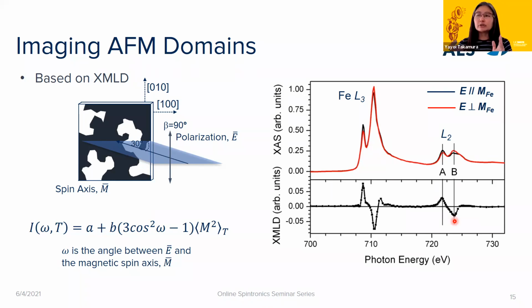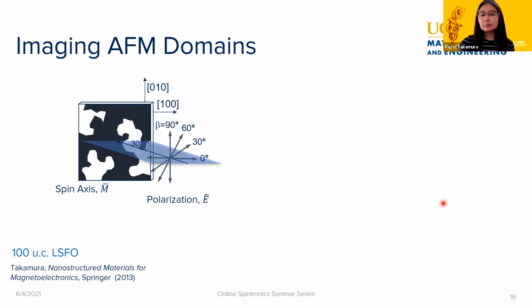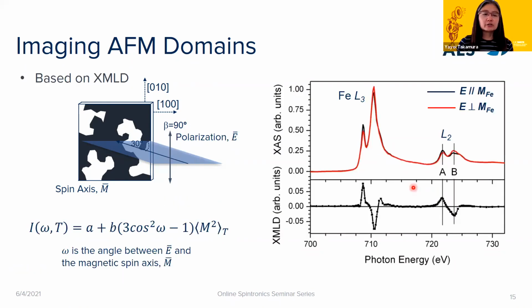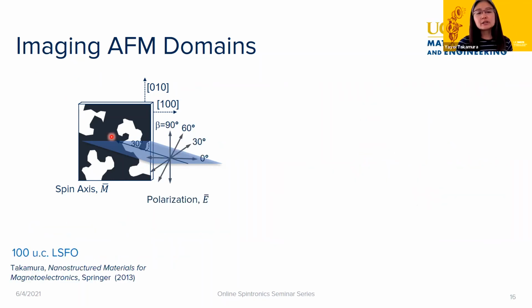And so then again, if we do this normalization, take the difference normalized to the sum, then we can get our dichroism picture. And so then what we'll get is that we can sort of map out locally what these antiferromagnetic domains look like. Okay, so that would be if we had one single polarization.